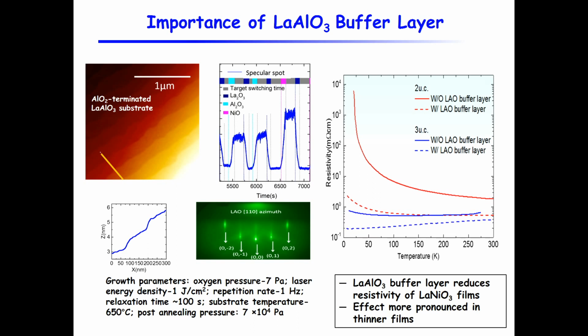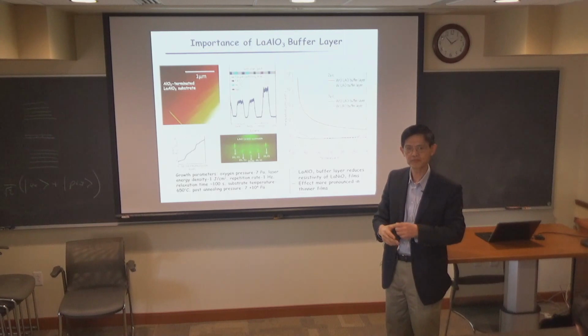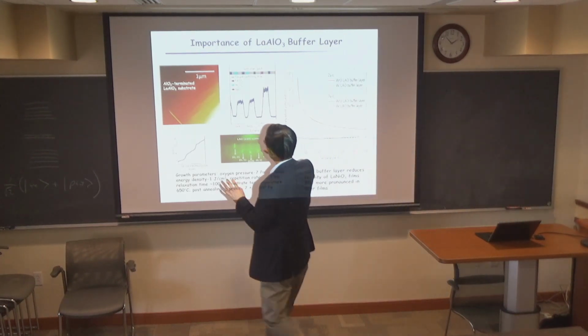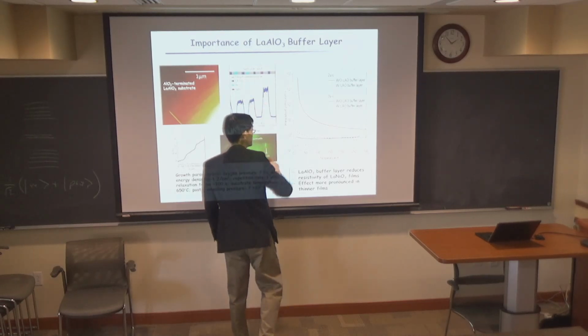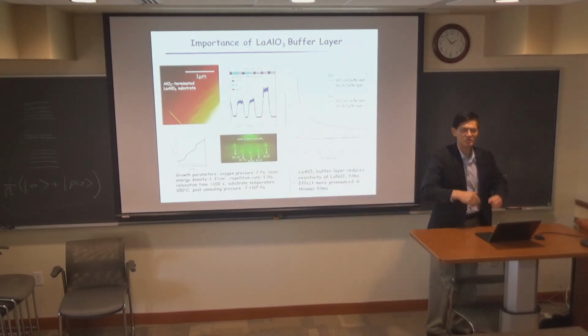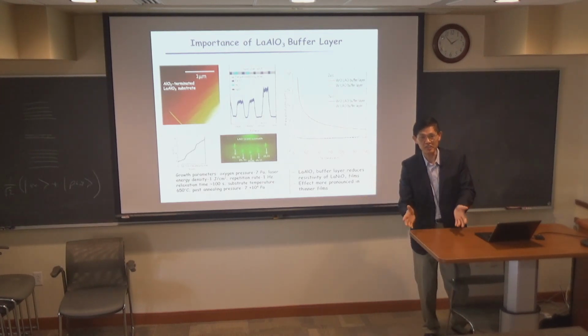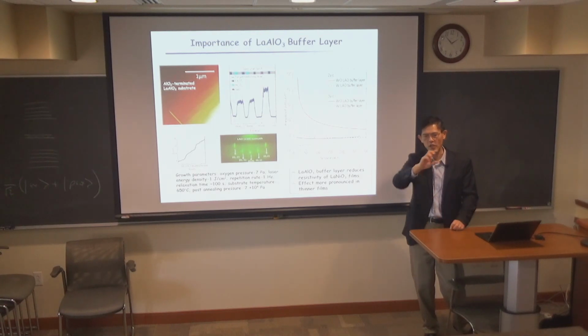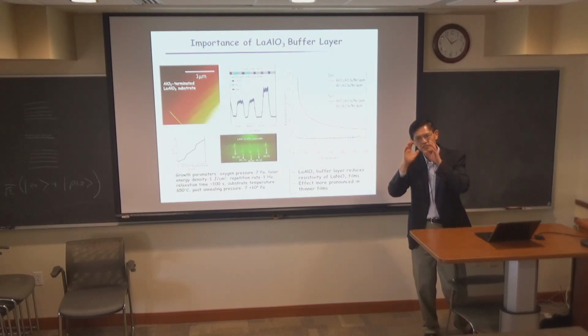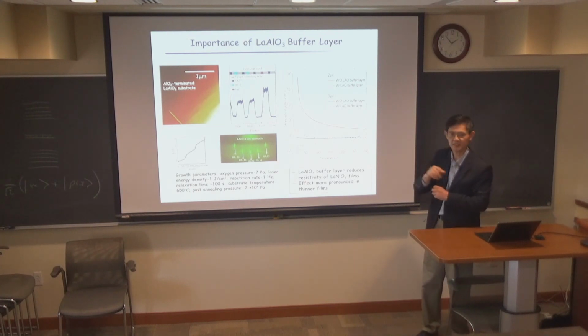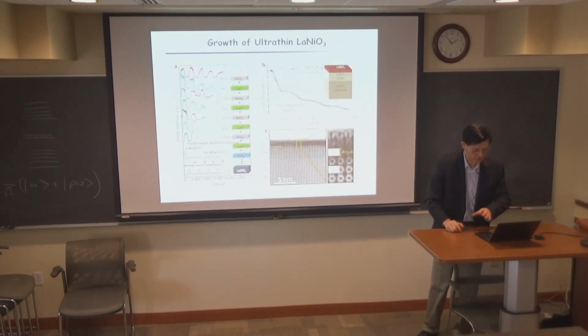But is that little switching thing the same time scale as the? Well, no, this is much longer than the time you need to switch. Okay, but this thing at the top is not drawn to scale. It is to the scale. When you say a few seconds, then it looks like you have a few hundred seconds. Oh, okay. So you're right to say that this is not exactly switching time. That should be switching time plus dwell time, or oxidation time, or something. Switching takes about 5 or 6 seconds. And then she just leaves it there before she applies the next layer. And she found that is important. That's a very good observation.